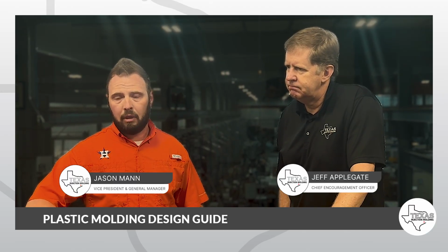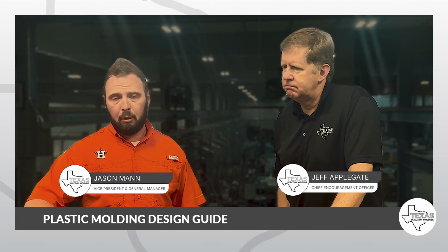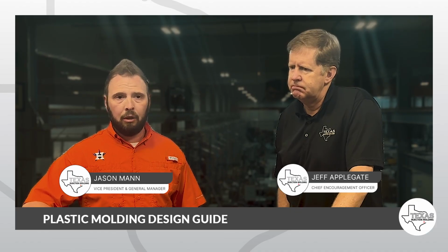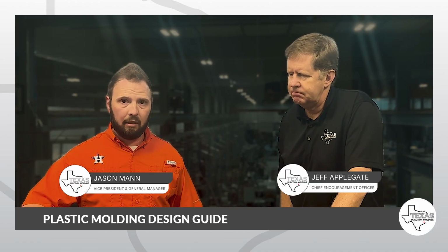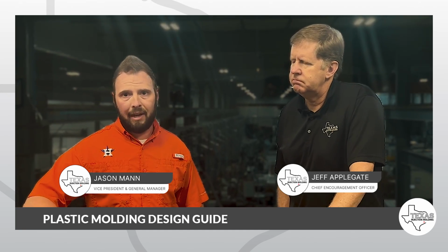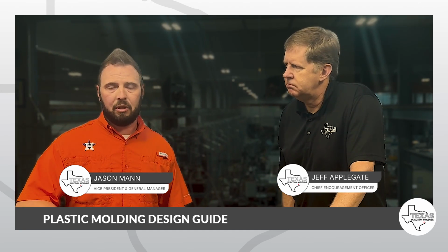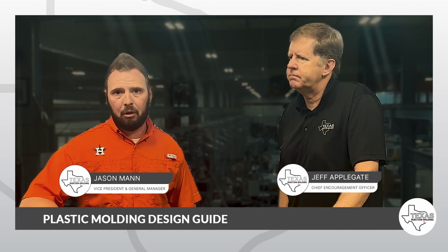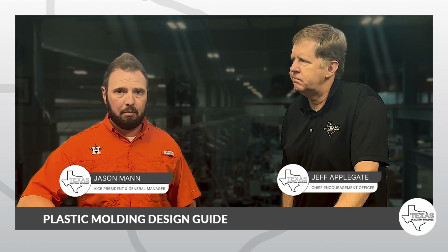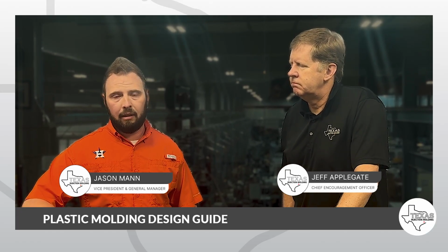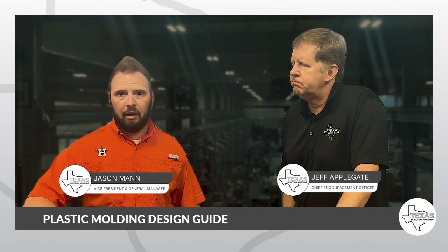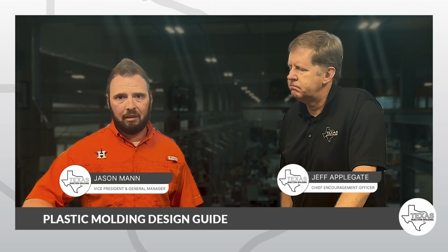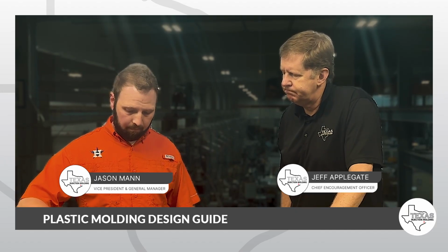Bosses are very important. They allow you to put inserts into the parts and use self-tapping screws. You can also use those as fastening mechanisms. So they provide a really important structural element to the part. But you have to be very careful because if your diameter exceeds 60% of the wall thickness, you can end up with sink marks on the exterior of the part, which cosmetically can be a very bad thing. So special care and consideration has to go into bosses and the design and location of those bosses so you end up with the best possible part.